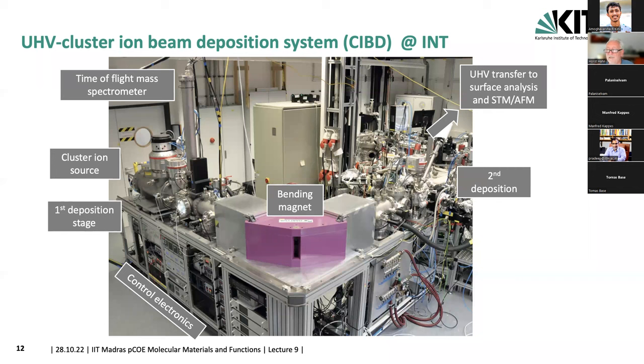And in order to protect this reactive film, we have another small evaporator over here. We can put a protective layer on top of that. Then here we have a bending magnet where we can size select or mass select the clusters, and then we can accelerate or decelerate them before they come into the second deposition chamber, where we can either deposit the size-selected clusters by themselves, without a matrix, or by using an e-beam or an effusion cell, we can deposit them into a matrix. And then finally, we can transfer the sample to a surface analysis and STM AFM system to do a first characterization of the structure.